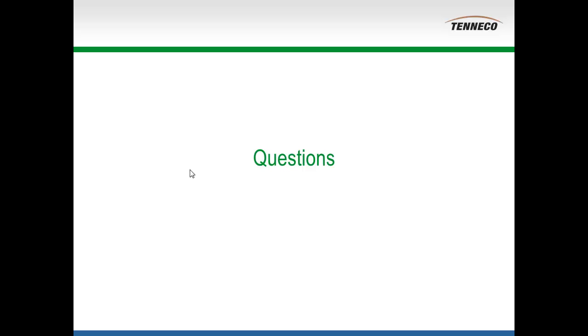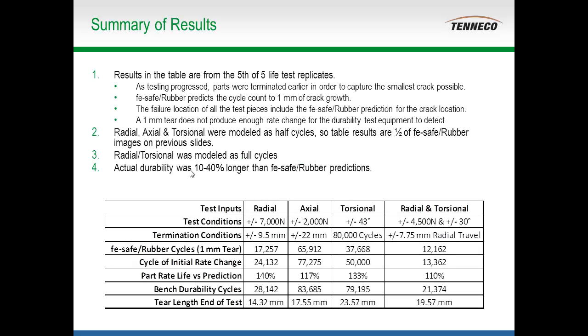Well, I guess one of the things, because my background's in materials and material science, and I also have a background in statistics. As I've talked to various people about how accurate I think the results need to be, these are promising, but I honestly think eventually we need to be within 10 or 15%. Because the best way to interpret, if I go back a slide, is that each one of these test cases can be thought of as an individual block of a block cycle. So if you have a 6 or 10 or 15 block cycle and we're off by this much per block, that may sum together being off by a factor of 2 or 3 for the overall test regimen.